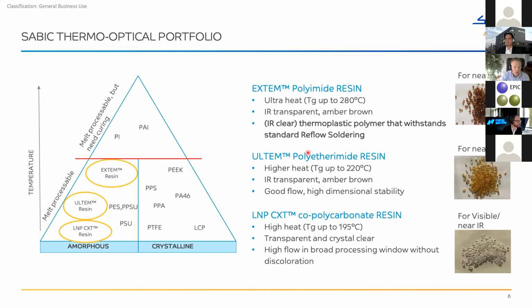We also have other polymers. I'm not going to talk about them today, but I just mention a few of them, which are also used quite a lot in this industry. Ultem is very well known to a lot of you. Tg is a little bit lower, but Ultem is used a lot in optical transceivers because of the high dimensional stability, so the low CTE. And we also have a copolycarbonate, similar to Covestro, but with a slightly different chemistry, where you can increase the Tg up to 195. This is water clear, and is used for lenses like, for instance, flash lenses, where you really want to have water clear transparency.